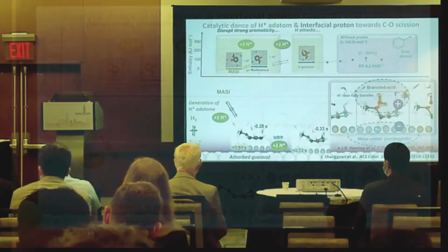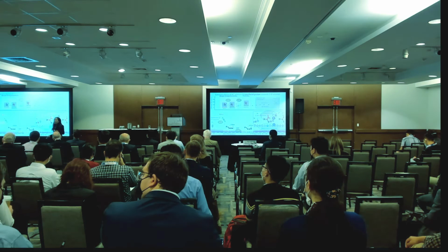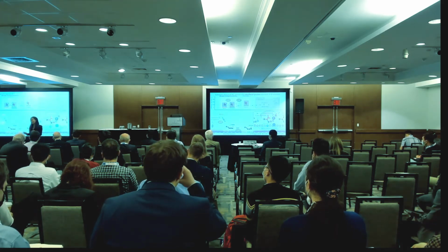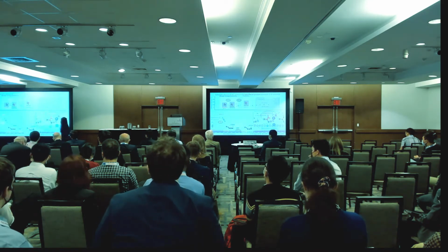So, the hydrodeoxygenation chemistry is actually quite complicated. It requires multiple hydrogen and proton involvement. How they are involved, what position they attack on this ring, really shapes the entire free energy landscape, and the reactivity. This requires a small jump. First hydrogen attack, second hydrogen attack, before you can cleave the CO bond. You cannot just jump. You need one step, two steps, you need proton involvement, you need hydrogen attack to weaken the aromaticity. That gives you the entire landscape over here.